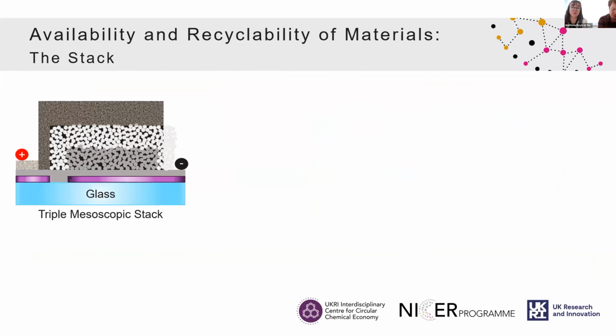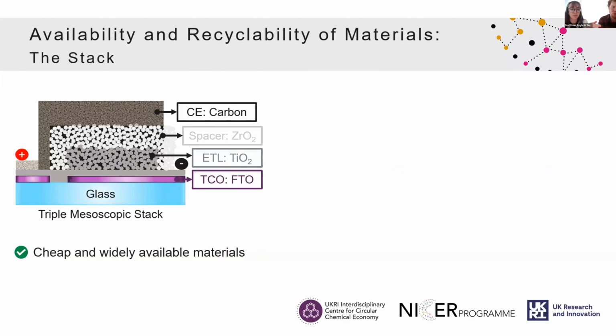Now, on to the second part of the device. So we've talked about the photoactive layer. Now we have to talk about the other layers that I highlighted before that in theory aid charge extraction. And those are also made of cheap and widely available materials. For example, you've got the counter electrode, which is in this case carbon. We've got a spacer, which we use just to prevent the carbon from touching the other side of the cell and creating a short. So in this case, we chose zirconium oxide. The titanium dioxide will help the charge extraction, the electron charge extraction. And then we have another, let's say, electrode, which is a transparent conductive oxide. In our case, it is fluorine-doped tin oxide.